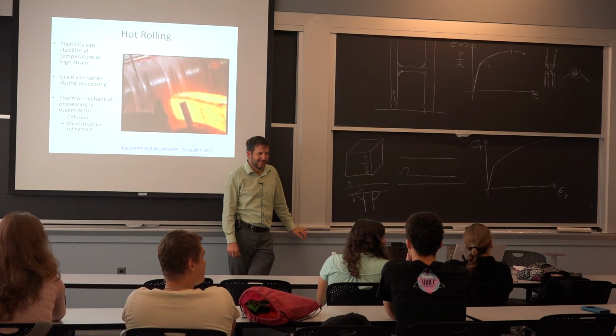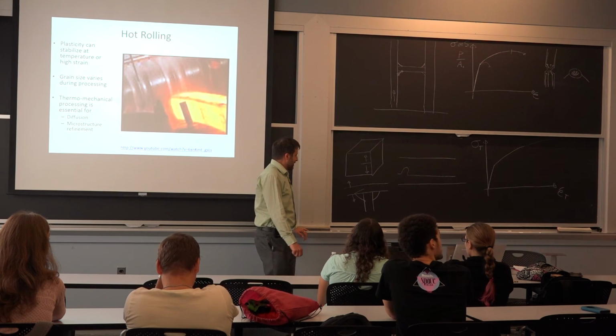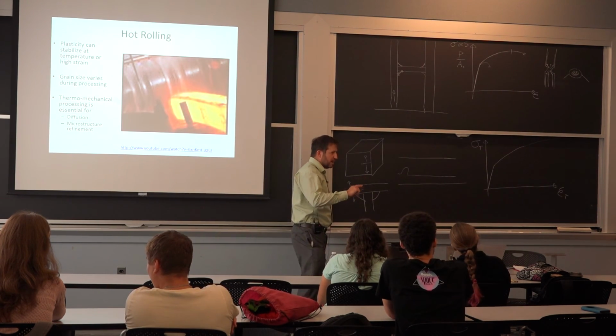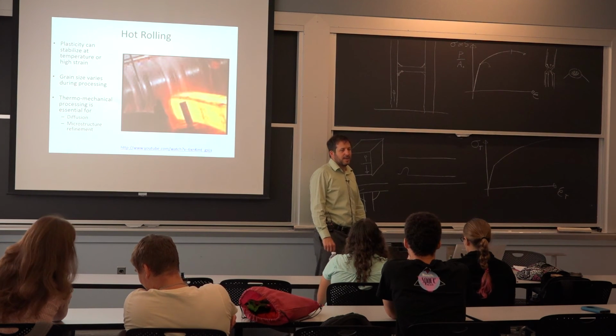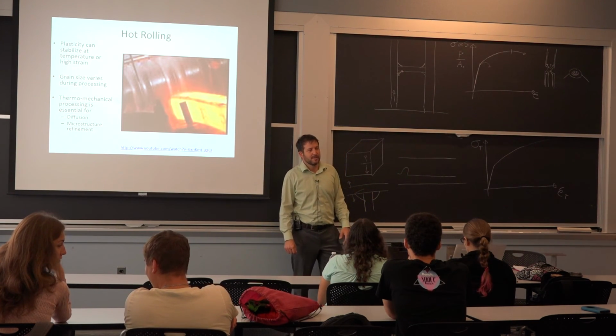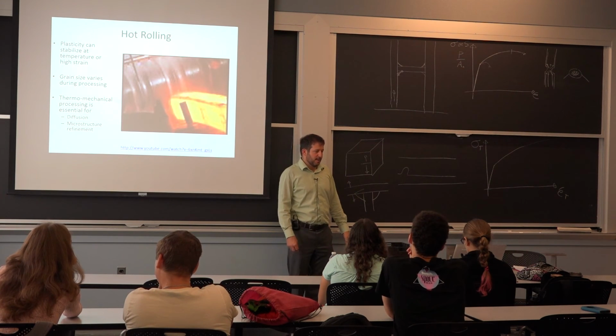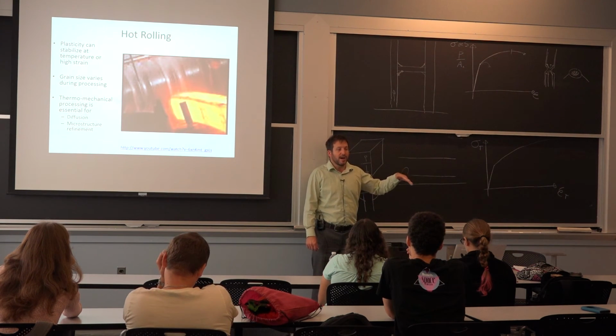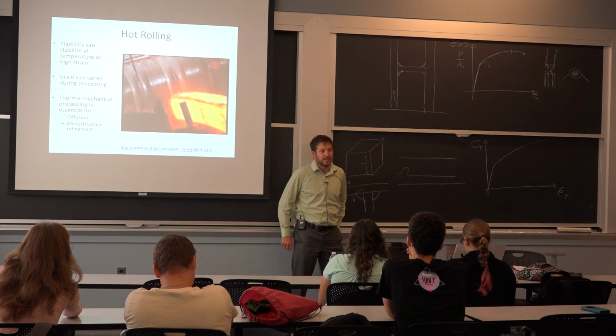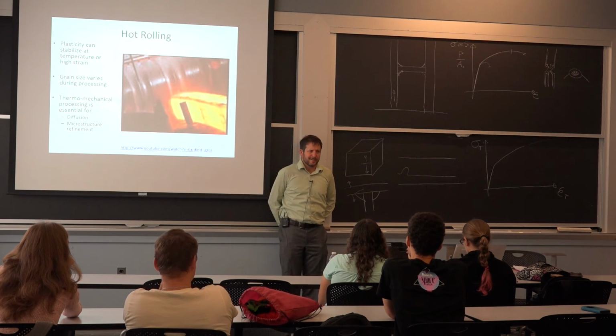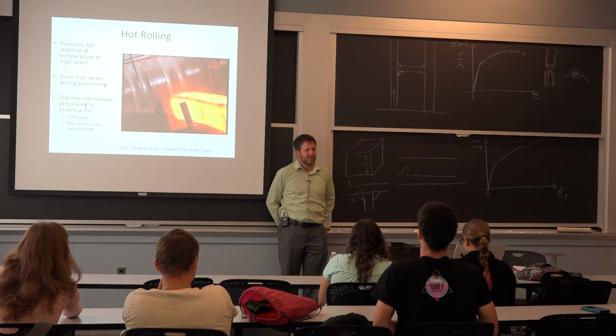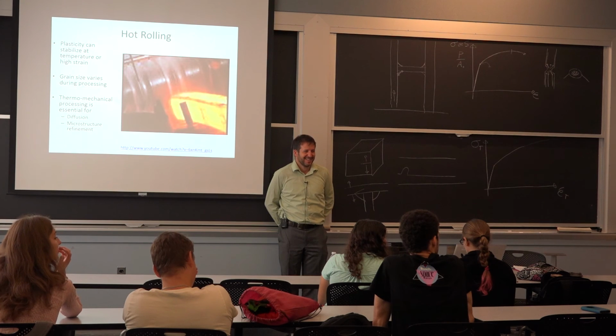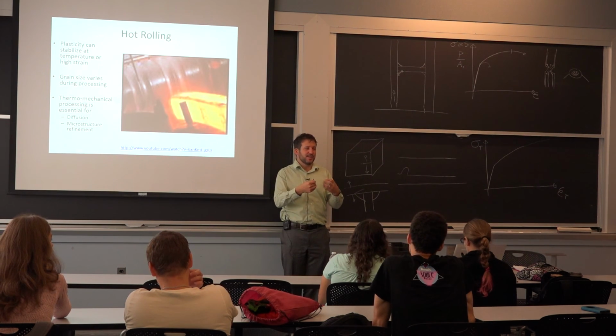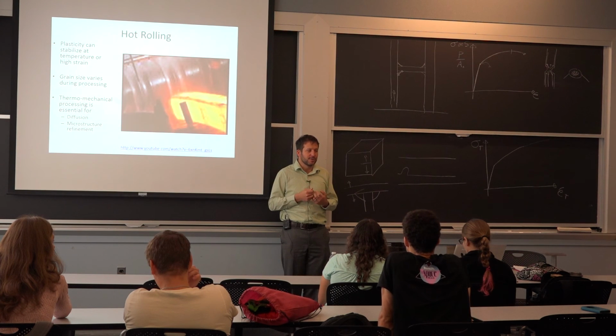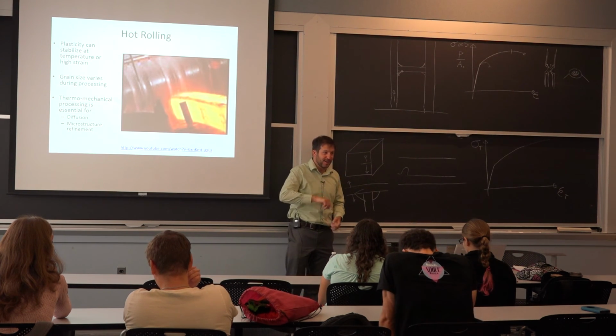Do inclusions localize at any certain Z depth through the thickness, or are they evenly spread throughout the thickness? They tend to be more in the center because they don't have this diffusion need, and that's a very good question. So right down the center line of a wire is where you expect the biggest pieces. Yes, that's really true. And I guess it's an advantage, right? For most cases, yeah. It's an advantage in terms of trying to get a crack on the surface if you don't cut it. Now, if you cut it in half, now you have the problem on the surface.